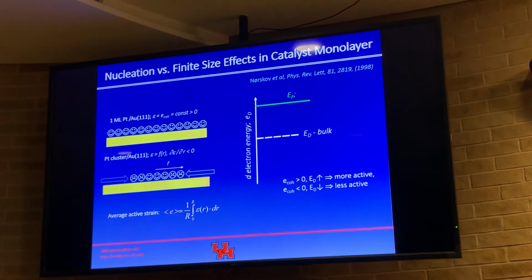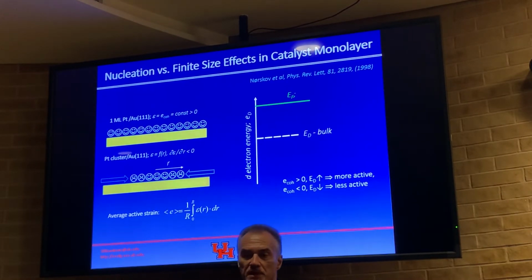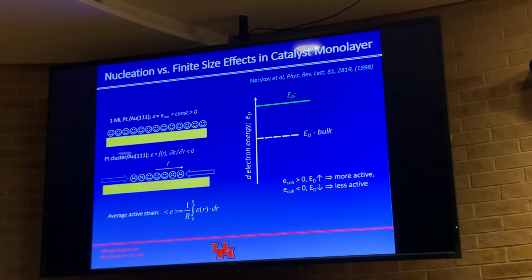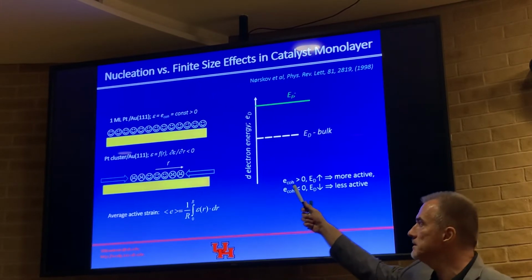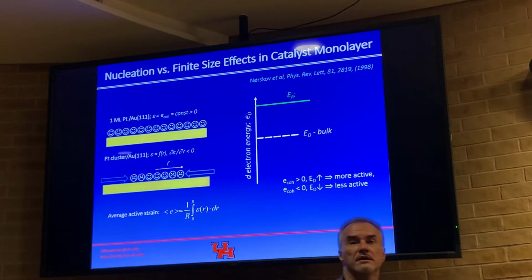to the situation where you have a perfect monolayer like this, sitting on your substrate with the epitaxial match, where the strain is known due to the epitaxial misfit and the electronic mixing and stuff could be easily addressed by DFT. What they don't tell you is that in reality there's only a few systems where you can make this. In reality, what you have is this, which is the finite clusters, small 2D clusters.